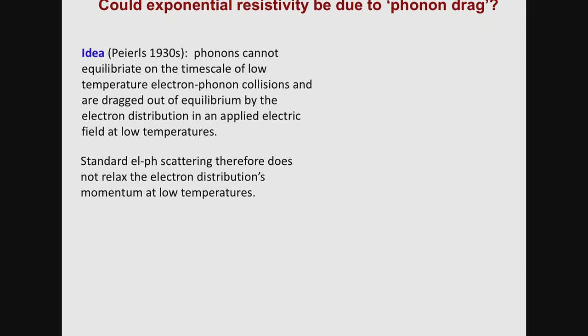And when Bloch wrote that down in the 30s, Peierls straight away said, that isn't what's going to happen. If the electrons are scattering strongly from the phonons, the phonons will themselves gather some momentum from the electrons. The electrons going out of equilibrium will drag the phonons with them. And that effect of phonon drag was looked for in many compounds. It's been quite easy to see it in thermal transport, but it's been very difficult to see it in electrical transport, partly because the characteristic temperature associated with the drag is much lower in most materials than it is here. But let me explain that for you a moment.